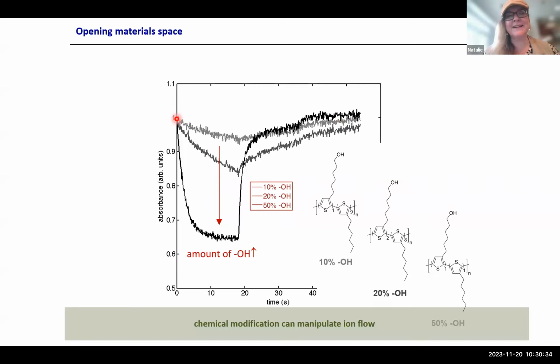And based on the slope, you can see essentially, well, it's a bit of an assumption, of course, the slower it is, the slower the ions get to the backbone. So here you see when you have more alcohol groups, not surprisingly, upon application of the bias, you get the ions in and you can more rapidly oxidize the backbone. So it's a bit of an indirect measurement of ion flow. Okay. Actually, it is shown here.